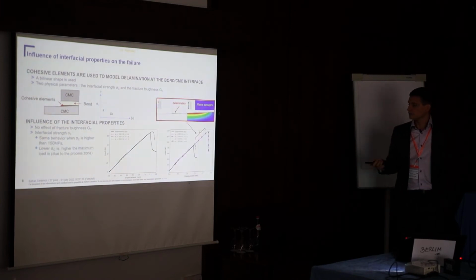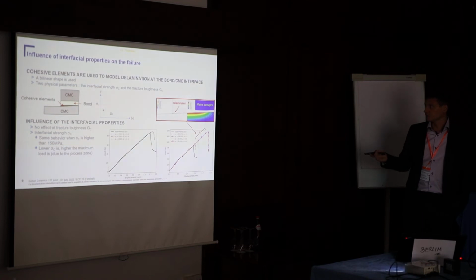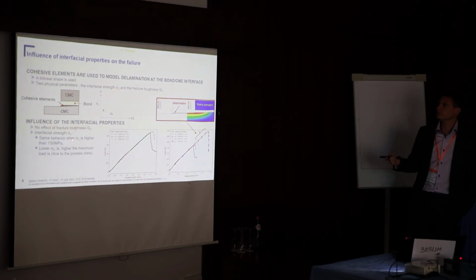But if we look at the influence of the interfacial strength, we can see two things. The first one is that we have the same behavior when the interfacial strength is higher than 150 MPa. So these are the red and the blue curves here. So we have just the failure of the yarn as previously. But we can also see that the lower the interfacial strength is, the higher the maximum load is here. So with the green and the purple curves, we can see that we have a different behavior. So we can have delamination here, and then the yarn failure.